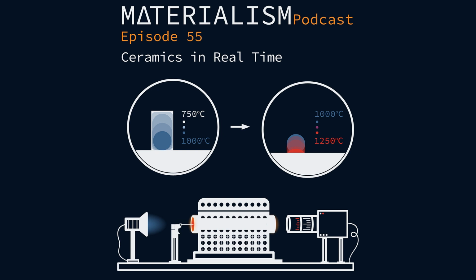The other way is to similarly avoid that the glaze is in too much compression, because if it is too compressed, when you cut the tile, it explodes and it starts cracking in unpredictable ways because there is too much energy inside. And the last one is always related to tension, which is predicting if the tile will be flat or not.